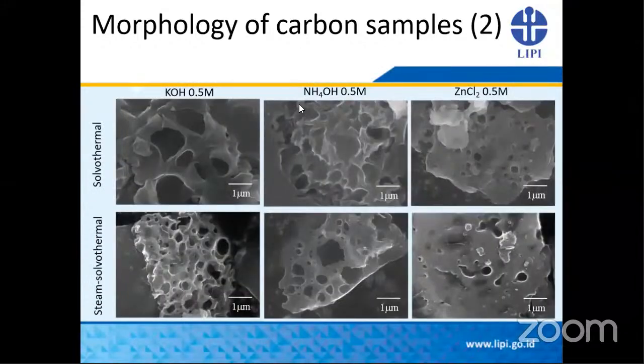So after that, we also compare using different solvent and also different setup. This is the solvothermal and this is the steam solvothermal. Solvothermal is when the carbon sample is immersed in the solvent, while the steam solvothermal is when we put the carbon sample above the solvent. So we just put some steam and vapor to modify the pore structure of the carbon sample.